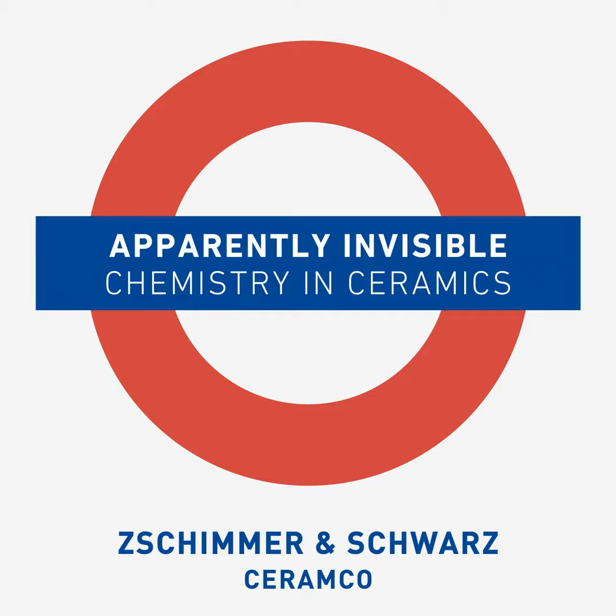Among those elements, resins are definitely responsible for the binding power that is required to fix the grit. You also need to know that these glues develop their action not only between the granules of the grit, but also between the grit and the layers of the tile support. The binding action takes place after the solvent has been partially absorbed by the ceramic support and, at the same time, once it has evaporated due to the high temperatures of the tile.